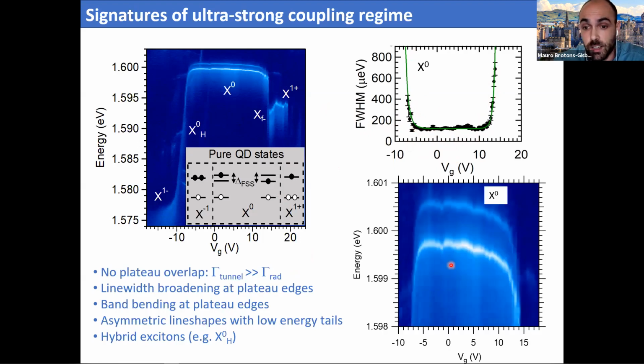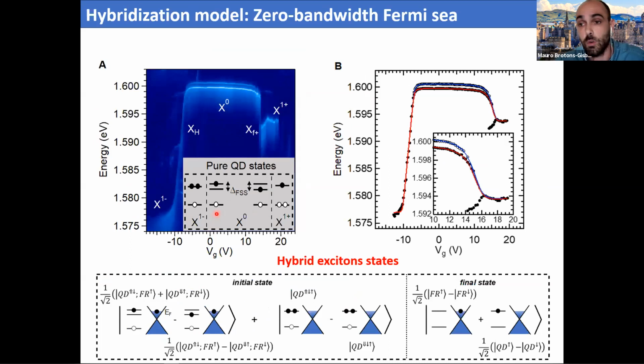We also observed a strong bending of the energy transitions. This is a zoom of this region here. Again, when we approach the voltage gate at which we have tunneling, you can see the band is bending to lower energies. And what is probably more interesting is that we also observe the presence of hybrid excitons, okay? These hybrid excitons are this continuous transition from the neutral exciton to the negative trion, for example, in this case.